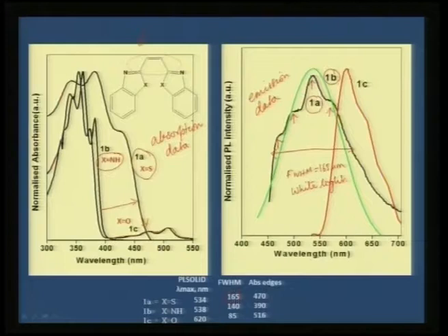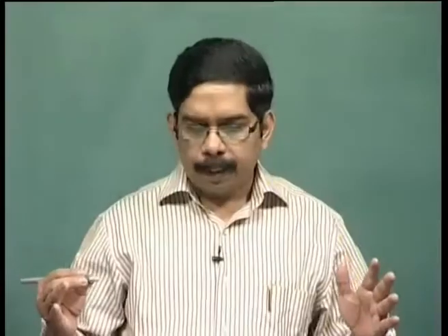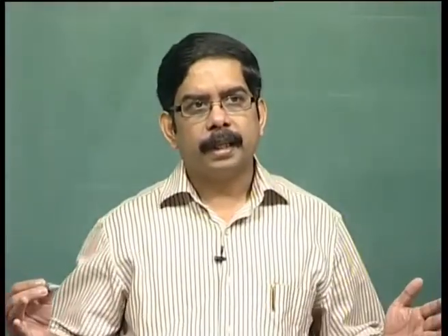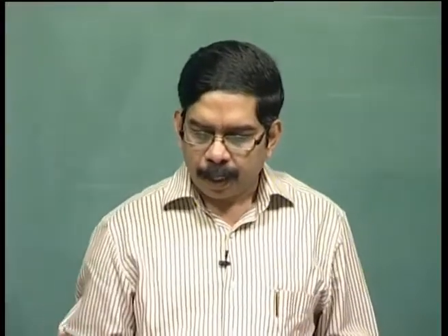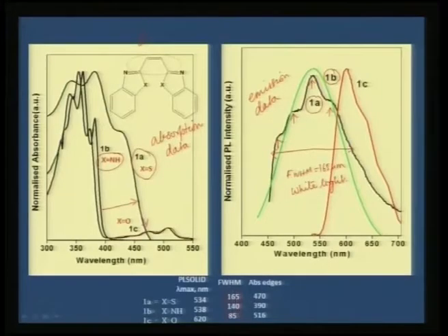Whereas if you look at the imidazole, although it is showing one peak, the full width at half maxima is considerably less, and the oxazole component shows a very narrow emission, and it is more preferentially in the red region. So we can clearly understand that the thiazole moieties seemingly have a widespread in the emission feature, and it is also showing fine structures in terms of emission.